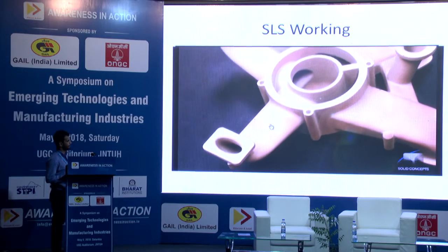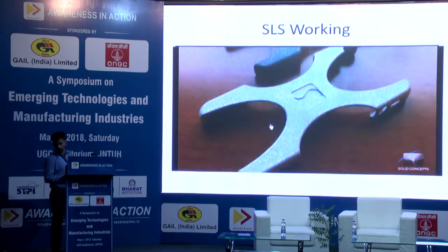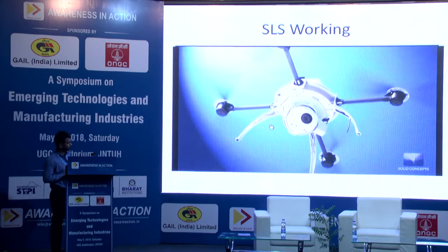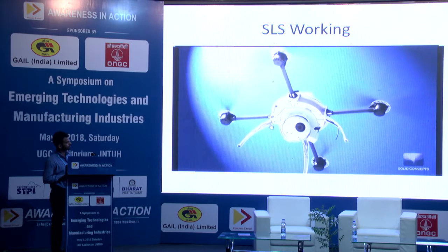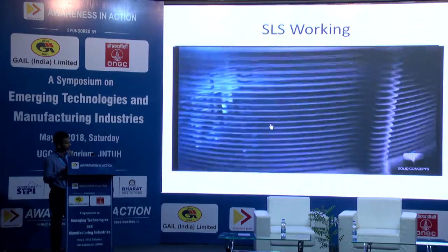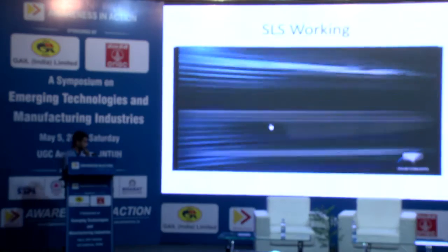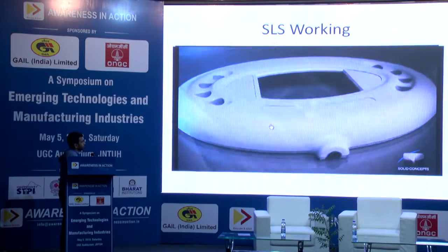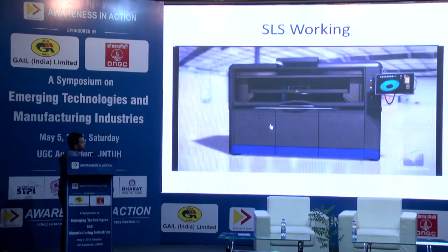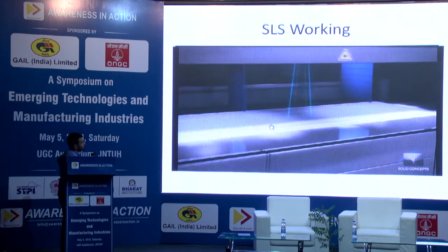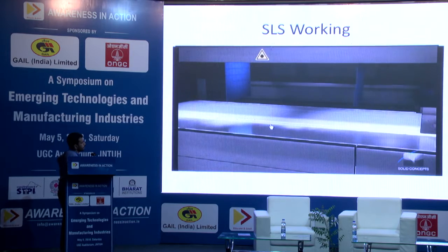Powdered nylon 11, nylon 12. Parts produced are lightweight, highly durable, and require no expensive tooling. The SLS process begins by splitting 3D CAD data into thin cross-sections or layers. The data is then transferred to the SLS Additive Manufacturing equipment. The machine then begins to create the first layer. After a leveling roller spreads a thin layer of powdered material across the powder bed, a CO2 laser traces the cross-section on the material. As the laser scans the surface, material is heated and fused together.